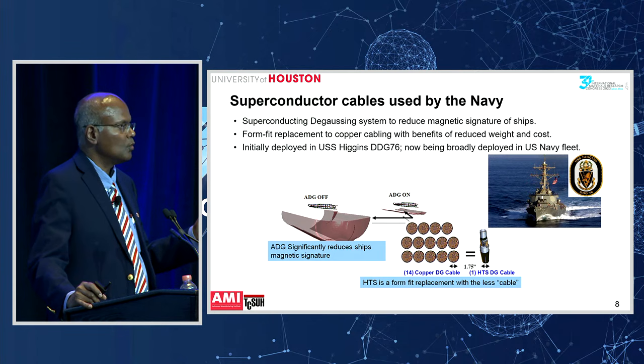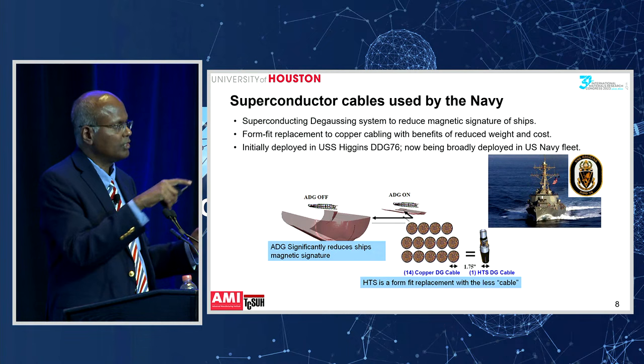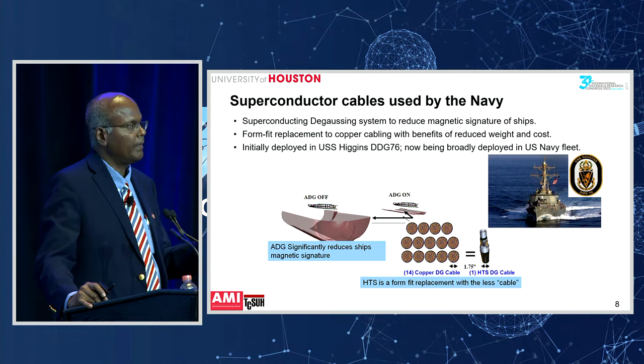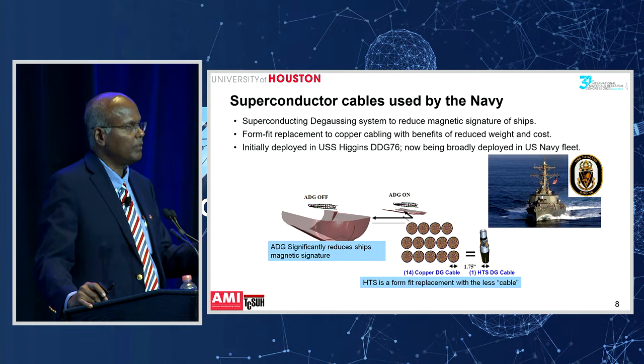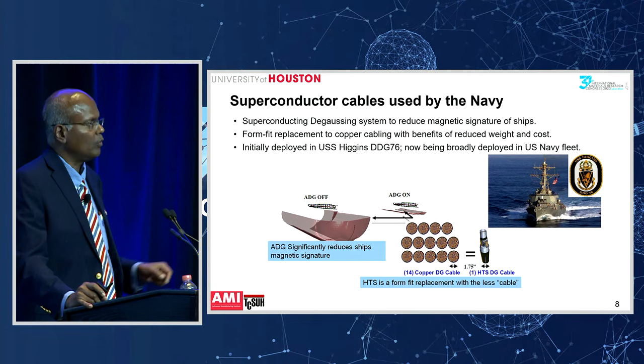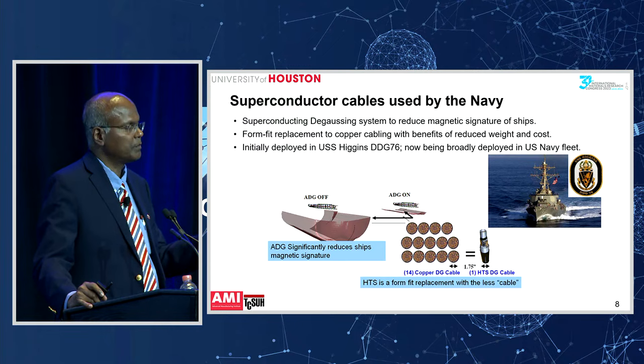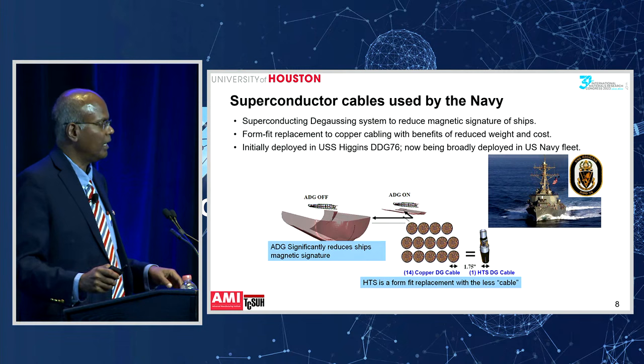So what the ships do today is they have large copper cables wound around the ship to act as a degaussing cable. They consume a lot of power, and they are also very heavy. In fact, more like 20 of these copper cables can be replaced by one superconducting cable. It's already been installed. You can see the USS Higgins already using these degaussing cables. And in fact, 5 more ships are being retrofitted with these degaussing cables. So this is already a practical application of the superconducting cables.